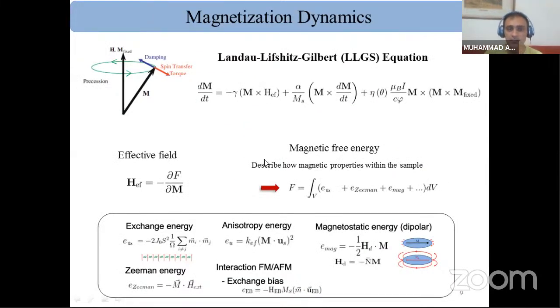Evolution of magnetization can be explained with the help of the Landau-Lifshitz-Gilbert-Slonczewski equation. The first term is when the moments are placed in a magnetic field, then they precess around the magnetic field. The first term of the Landau-Lifshitz equation explains the precessional motion without any loss. But experimentally, we see that there is a loss when the moments are placed in a magnetic field. This second term is added because of the damping of this precession of moments. And then the third term is called the Slonczewski term, which is a spin transfer torque term.